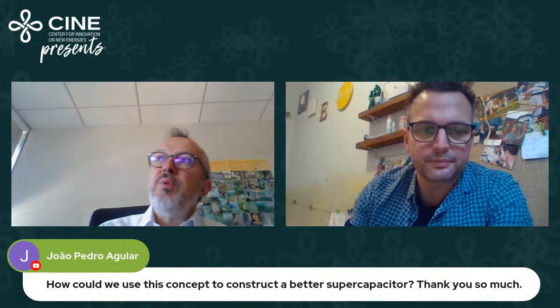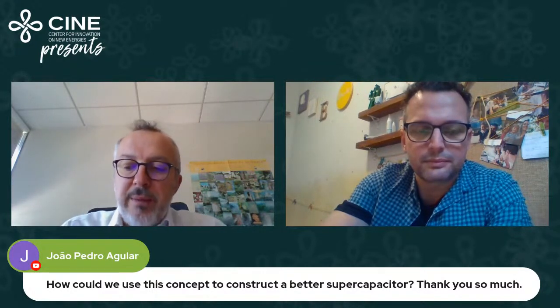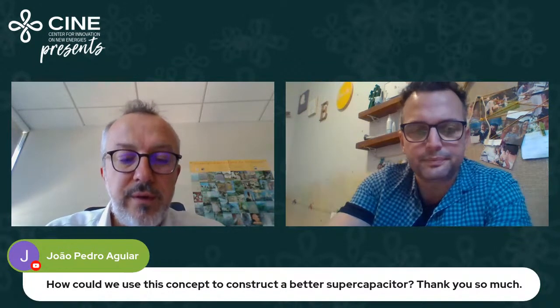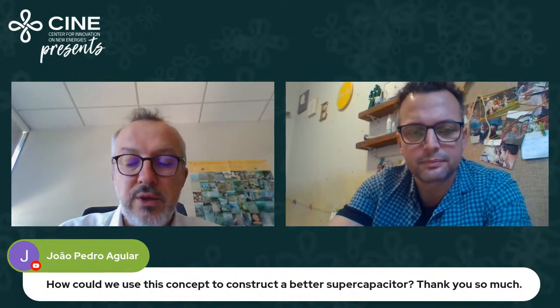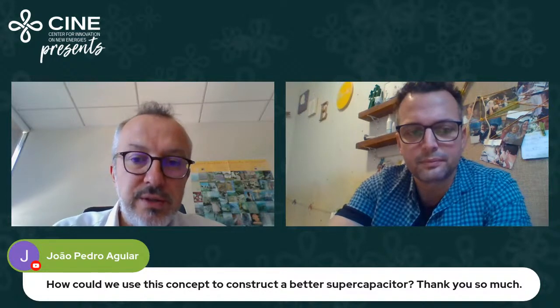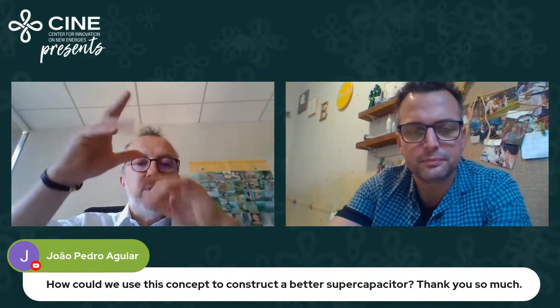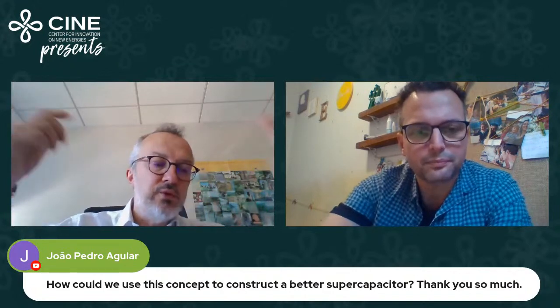Surprisingly, these supercaps are still very high power, and there are a lot of modeling papers saying that yes, the diffusion coefficient in nanoporous carbon is less than in the bulk electrolyte, definitely, but surprisingly faster than expected. This is because when electrolytes are confined in these pores, it is like a sponge. You have small pores, but close to them a slightly larger pore, and all the pores are connected. So it is not that difficult for an ion to move from one place to another. Yeah, that's good. So let's move to another one.